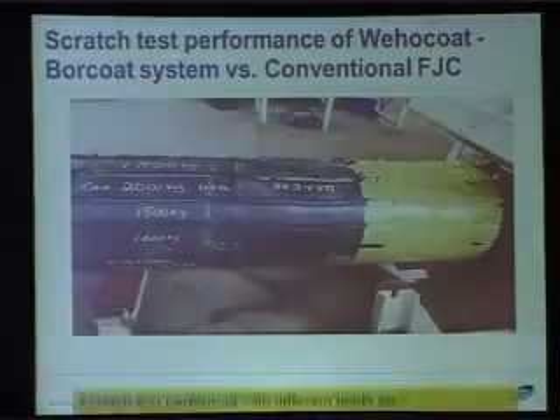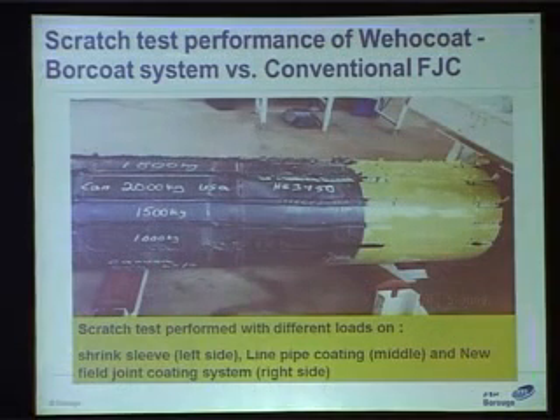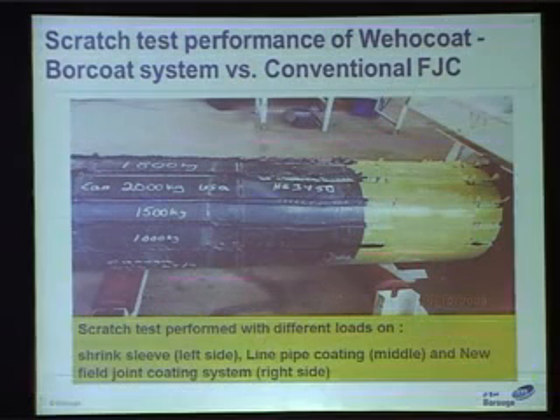These are from the project of Gasum, the National Oil and Gas Company in Finland, for a 90 kilometer 500 mm 80 bar gas pipeline. Now, why did Gasum select this? Because they had a test rig where the pipe coating is scratched by stones cast in concrete, and up to 2 tons load can be put on those concrete slabs below which the pipe is pulled. So they evaluated shrink sleeve, line pipe coating and this new field joint coating, and they found the performance is excellent. Since they projected many HDD sections, therefore they simply changed over from the conventional field joint coating to this kind of coating.